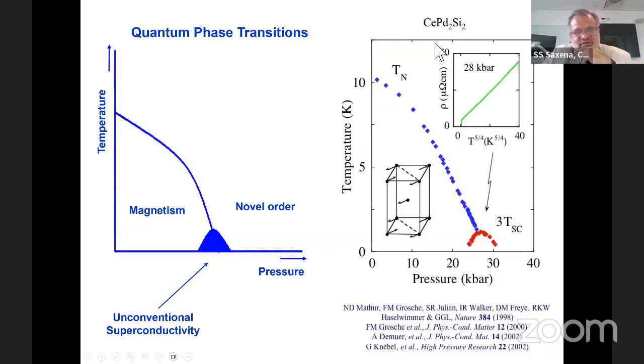And here is an example, a very old example now, published back in 1998, of superconductivity in cerium palladium 2 silicon 2, which is an intermetallic antiferromagnet, which orders at 10 Kelvin. Then with application of what today we'd say are very simple pressures, but back then relatively high pressures, superconductivity is found exactly where magnetism was suppressed.